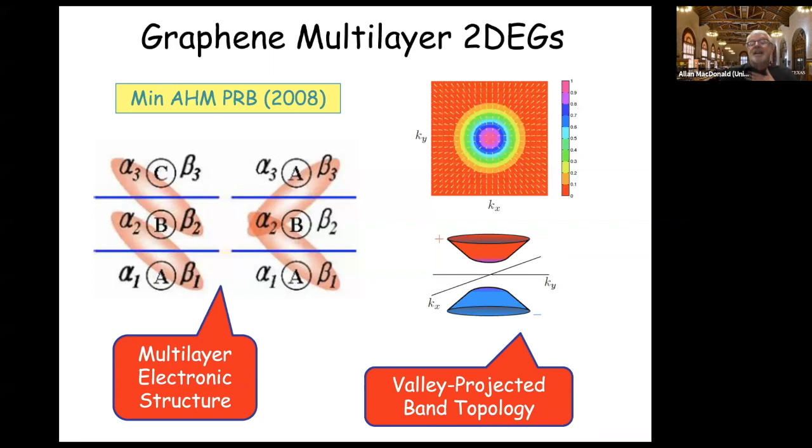As indicated by the color code here, which is the sublattice or layer polarization of these states, they have a strong tendency to break symmetries, which opens up a gap in the spectrum and polarizes the band states to one layer or another. That opening of a gap and the spontaneous layer polarization is necessary to get a non-zero Berry curvature for these states